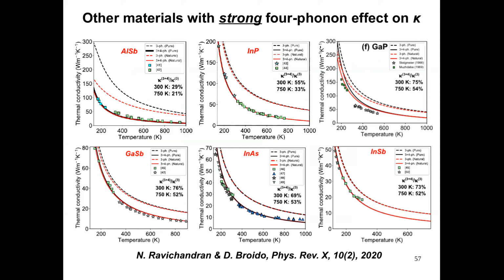In fact, we have calculated the thermal conductivity, including 4 phonon scattering, for a broad range of materials spanning the entire 3-5 family. And we find that for a number of materials, 4 phonon scattering, that is beyond the conventional theory, is very important. As you can see in these pictures, the solid lines are my calculations in this new unified framework, and the dashed lines are the conventional picture.